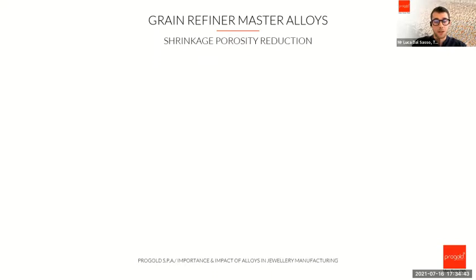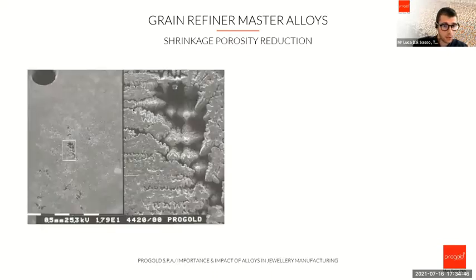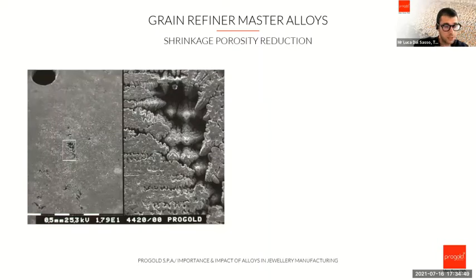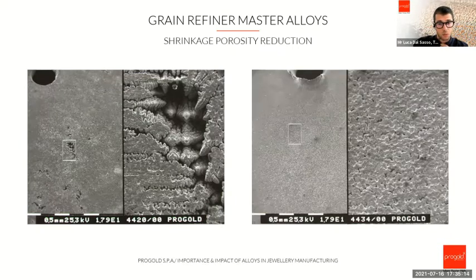Thank you very much. Here we are having a deep look at the pores. You can see on the left side the traditional alloy: as Damiano just told us, the pores are just a few, but they are really, really deep. So how much precious metal are we going to lose? How much must we remove from the sample in order to eliminate the defect? This is the real question, because on the right side you can see that the pores are a larger number, but they are less deep. So it will be much easier and faster to remove them.